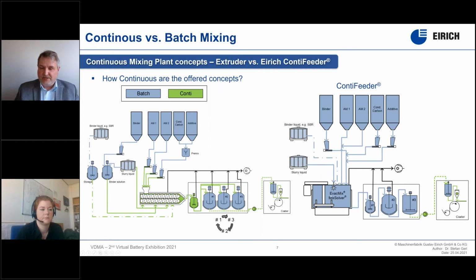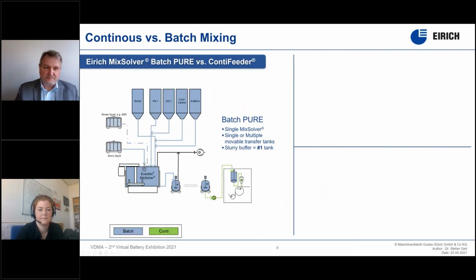And by this we can combine the strengths of a batch-wise system, that we can individually weigh out our material, adapt the parameters, and optimize the slurry preparation. Then we transfer it into a storage tank, and from here via buffer tanks to the coater, and the continuous supply is then from the last tank to the coater. If you compare how this looks with a pure batch process, it is almost identical.